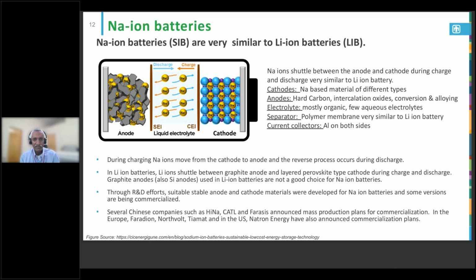Cathodes are sodium-based metals of different types, and anodes are hard carbon, some intercalation oxides, conversion alloys. There are 3 different types. And cathodes, I showed you, there are 3 different types there too. Electrolytes, most of them are organic. There are a few systems with aqueous electrolytes also. And the separator is a polymer membrane, very similar to a lithium-ion battery. And one difference is the current collector. In a lithium-ion battery, you have a copper current collector on the anode side and aluminum on the cathode side, whereas these batteries use aluminum on both sides, which is cheaper and also easier to maintain.